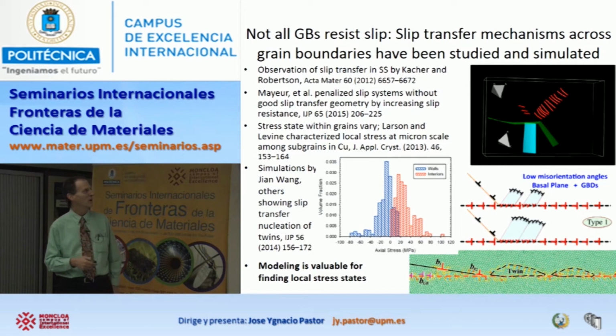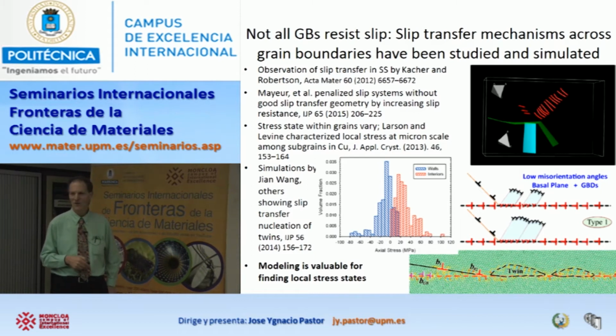Sometimes slip can just go right through a grain boundary and just go on to the other side. So this is actually an image, a model built from a TEM foil by some folks who've studied this in great depth, and have shown that if I have dislocations coming into a grain boundary, I can have dislocations going through on the other side, right, where they come in. And sometimes dislocations go off in a different direction in the same boundary. Also, some folks who have modeled twin nucleation at a grain boundary have shown that dislocations coming into a grain boundary can stimulate the nucleation of a twin at a grain boundary. And also, just the stress state within grains can vary whether we're in the interior of a subgrain or in the walls of a subgrain, the stress state can vary quite a bit. So it's really pretty complicated inside of a grain.